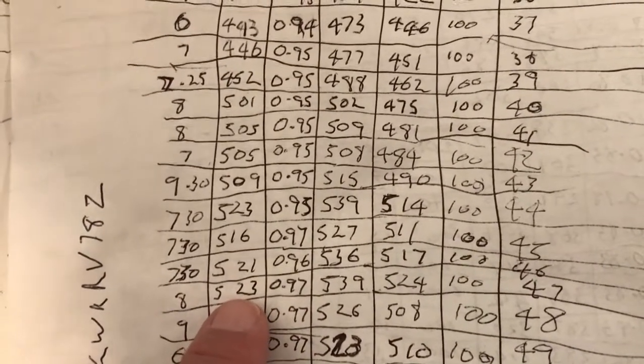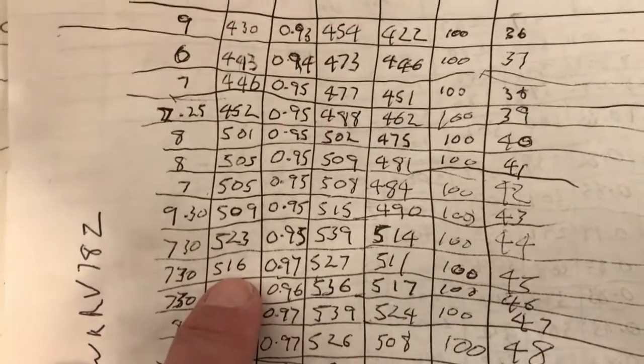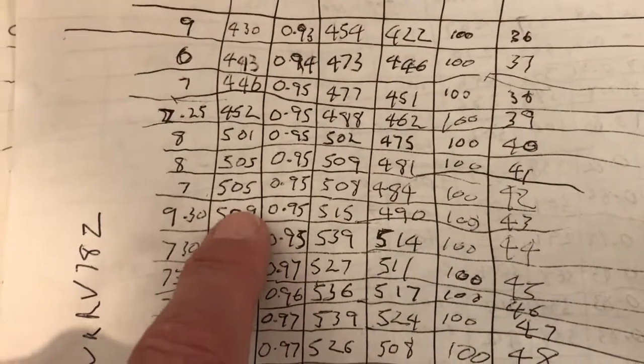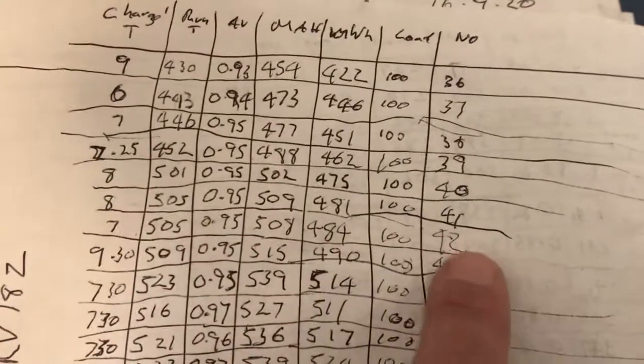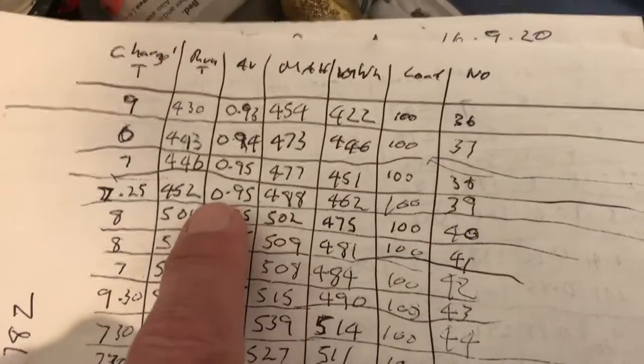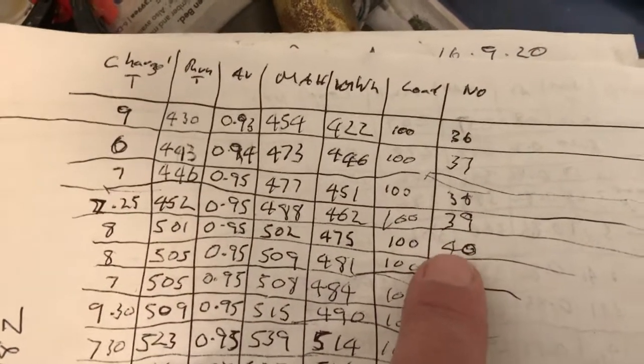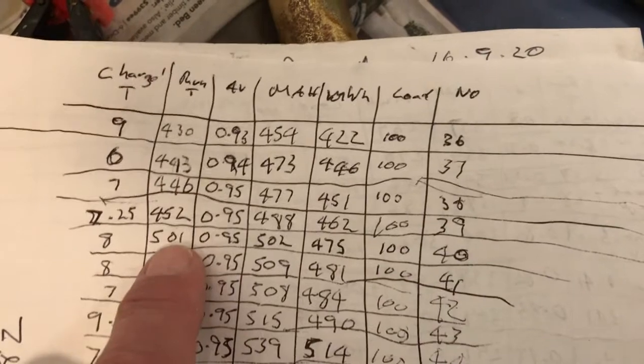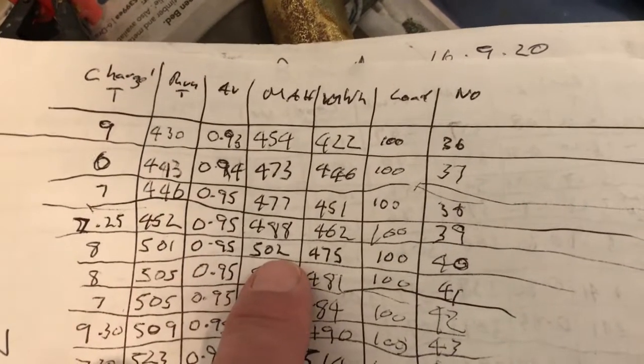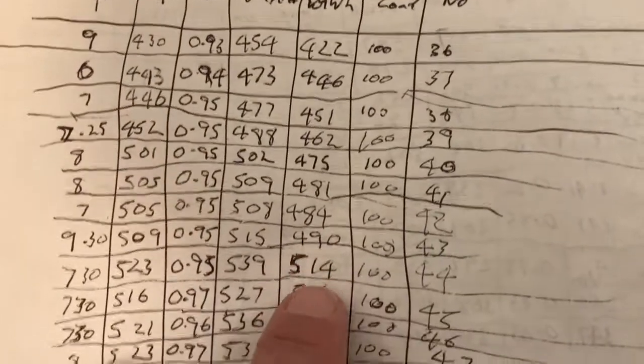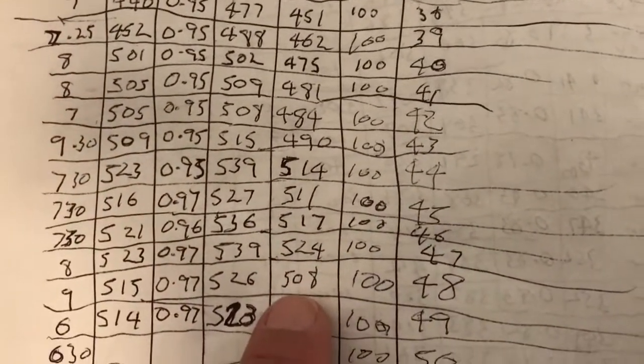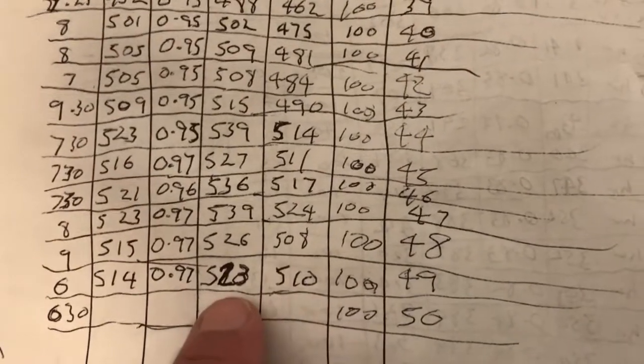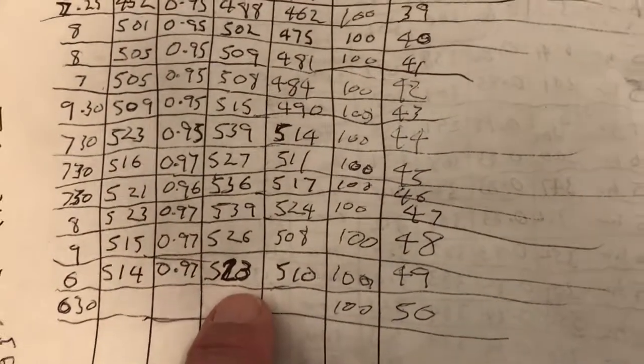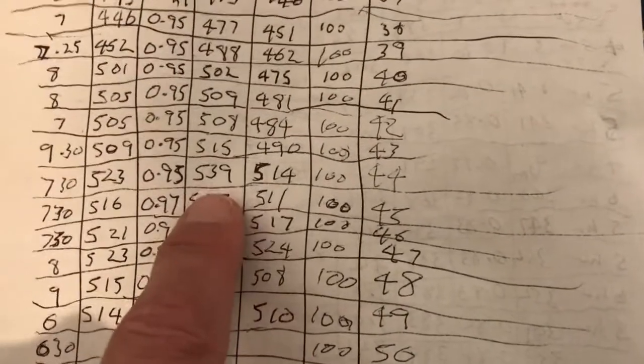Sometimes it runs for 5 hours and 23 minutes, 5 hours and 16, 5 hours and 9, 5 hours and 5 on the 42nd charge. Before that, on the 39th, I think 40, it started running at 500 milliamp hours and milliwatts, and slowly the milliwatts also went up. Now we're also up at 500 milliwatt hours, and 523 was last night's run. Should be somewhere around here and here for the cell. So I'm pretty happy with the cell's capabilities.